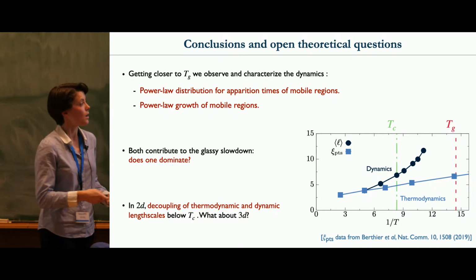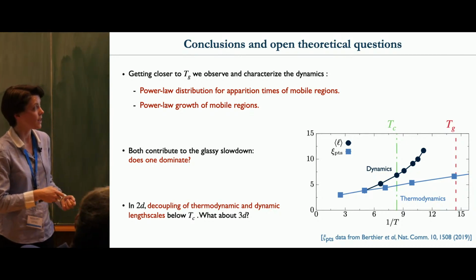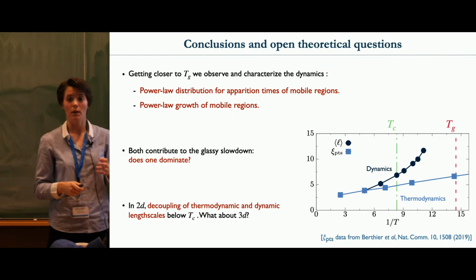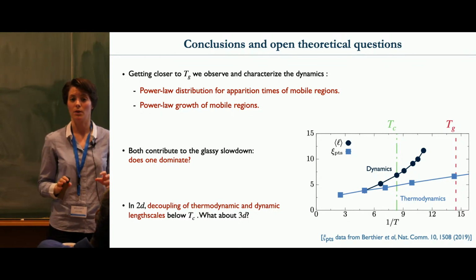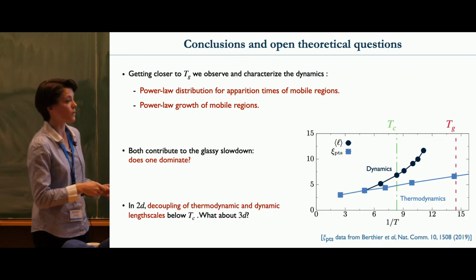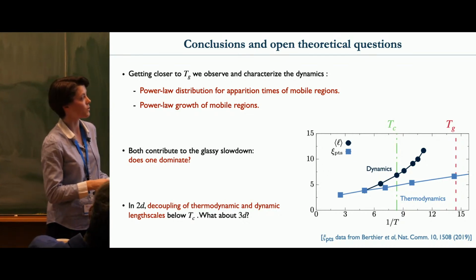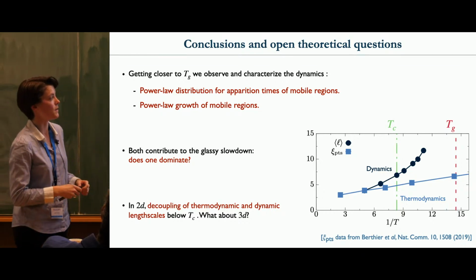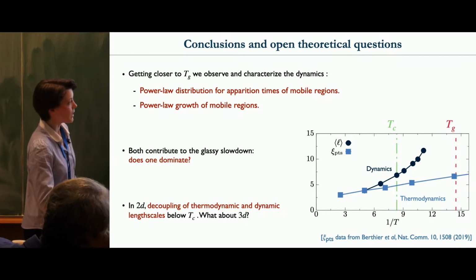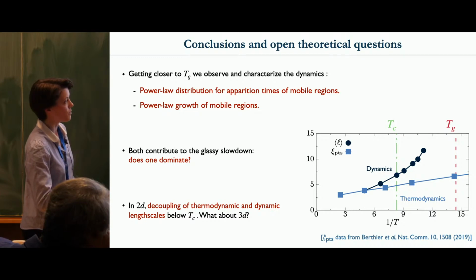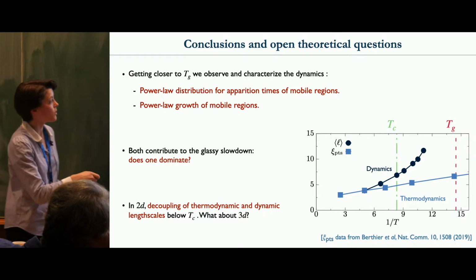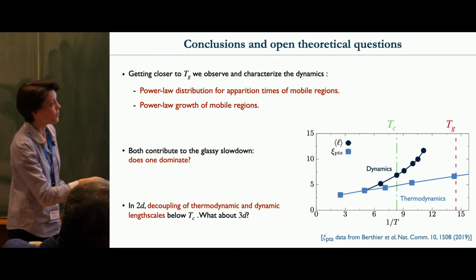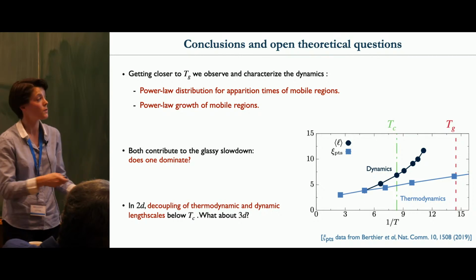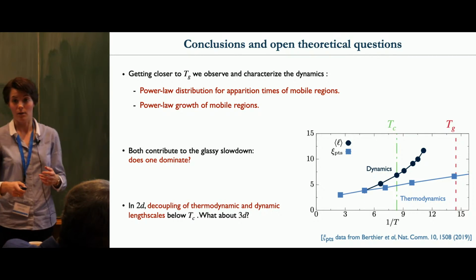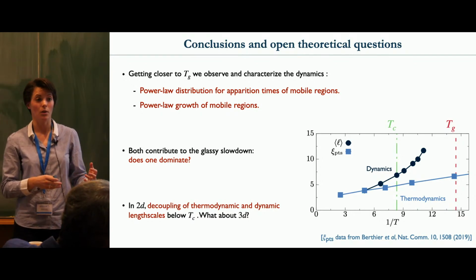So here in these new simulations, what we're able to do is to also inform and provide new data in this new regime. So here I'm showing two length scales. The first one is the average length at the alpha relaxation time, so when half of the particles have relaxed. And the second one is a thermodynamic length that can be measured. It's the point to set length scale, and Olivier presented it in the beginning. So I think that the data that he showed correspond to this regime here, so at temperatures that are higher than the mode coupling crossover. And there was a question, he said they decouple, but there was an open question, maybe at lower temperatures, the thermodynamic length scale increases and catches up with the dynamic one or not.